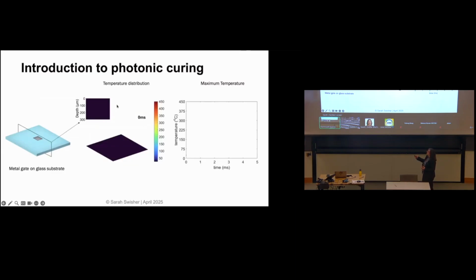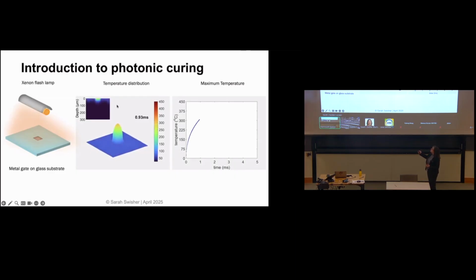So we can look at the temperature here, first as a function of depth. This is going through the substrate down this way. And this figure here is going to show the temperature variation across the substrate. So I want you to see what happens when we turn this light on. As soon as we turn the light on, we start to increase the temperature just locally, right where this metal gate is. So you can see the temperature reaches a peak, and then when the light comes off, the